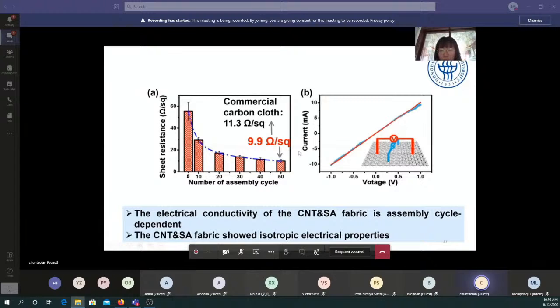It is notable that the carbon nanotube fabrics show isotropic electrical properties by the IV curve. This is because of the random distribution of fibers in the woven fabrics, and the isotropic electrical properties are important for the practical use of the fabric.